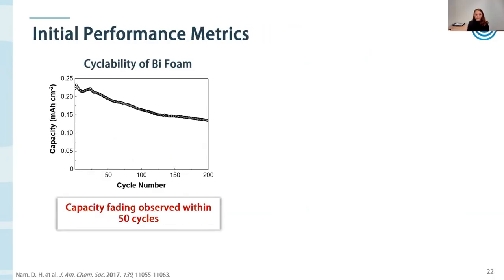One thing that is really important when you think about electrochemical systems is long-term stability. And so to evaluate long-term stability, we monitor the salt removal capacity, which is on the y-axis here, as a function of cycle number, the number of chloride removal and release cycles that we're doing. And so even though we were able to prove that we made this bismuth oxychloride phase, we saw capacity fading within 50 cycles. We started to lose some of our active material really, really quickly.